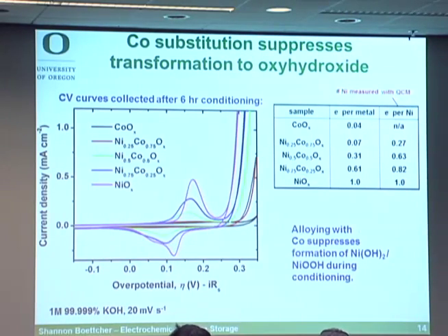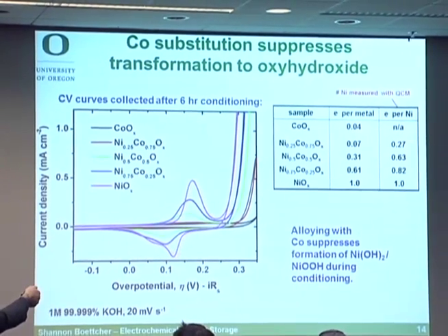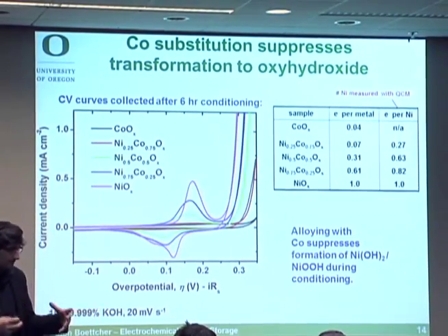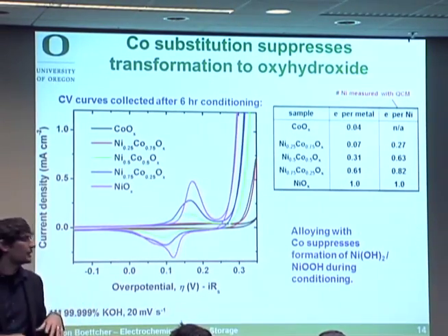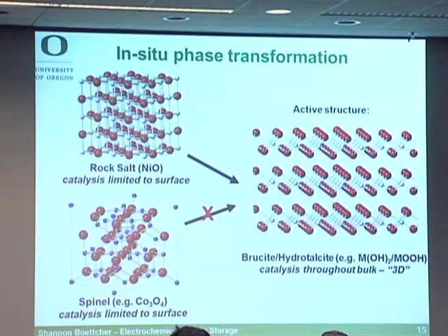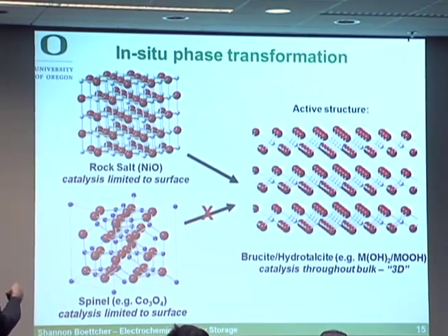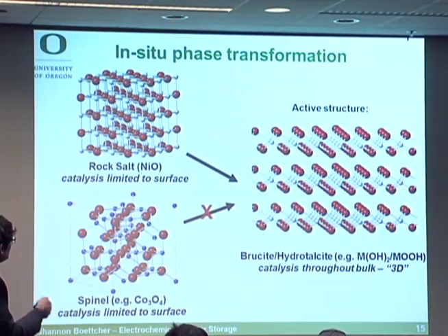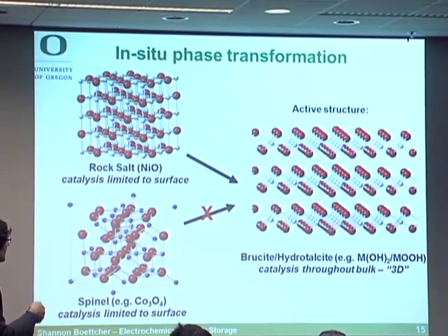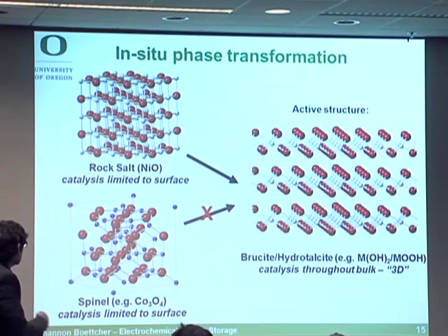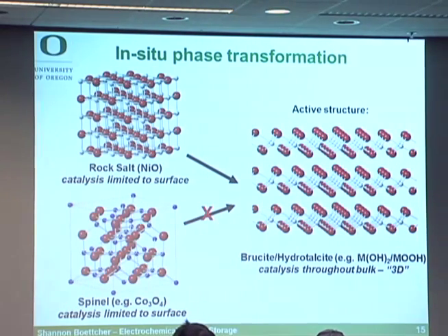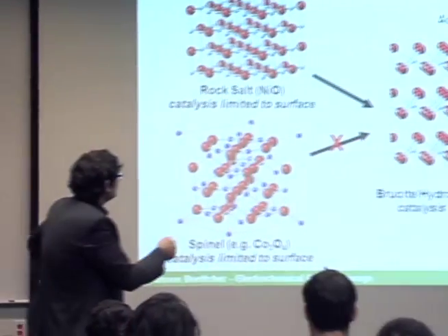But if you add cobalt to the film, it's suppressing that phase transformation. So the nickels are actually getting protected within the cobalt spinel matrix. What we think is going on here is that if you have this pure nickel oxide phase, it actually wants to become an oxyhydroxide, a hydroxide phase. This is a brucite structure, a layered structure, and this phase transformation happens. If you have a lot of cobalt, you start making this spinel phase. You can see this in the diffraction, and it doesn't transform in situ to this type of structure. Okay, so that's very simple.